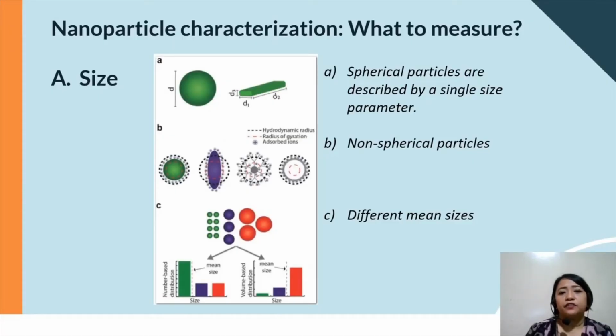In nanoparticle characterization, what do we measure? We first look at the size. Spherical particles are described by a single size parameter, and if the particle is non-spherical, we measure at least 2 of the dimensions, and then we take the different mean sizes and tabulate them as such. And in recording the particle size distribution, we measure at least 100 particles and then make a tabulated graph showing the size distribution of these 100 particles.